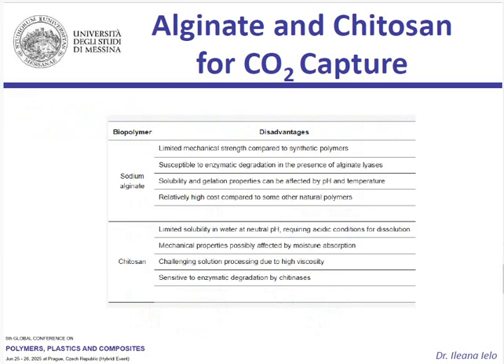However, like all materials, they come with certain challenges. They can exhibit limited mechanical strength, which might affect their durability in demanding applications. There is also a possibility of enzymatic degradation over time, and their solubility and gelation conditions are highly dependent on pH, requiring careful control during material synthesis and application. Despite these points, the outlook is very positive. These chitosan and alginate-based materials possess excellent properties for the reversible absorption of CO2, further improved by appropriate chemical modification.